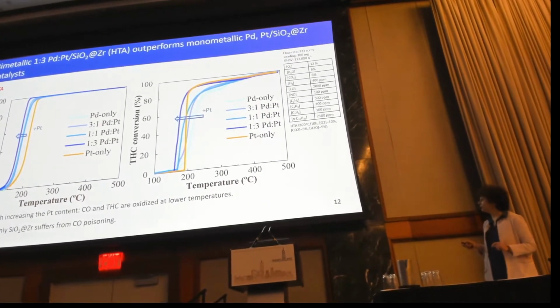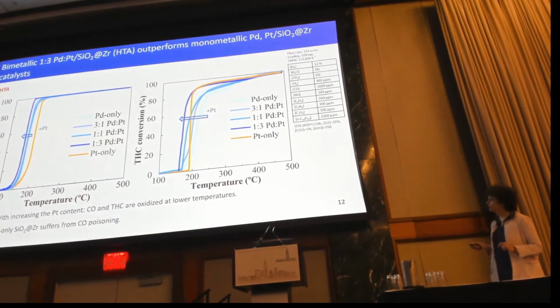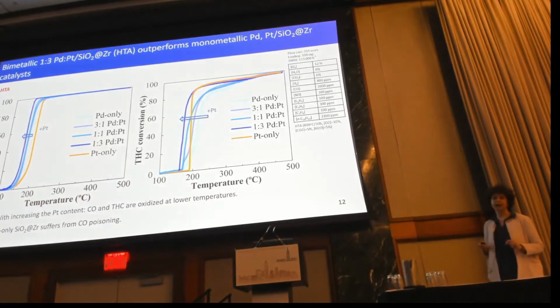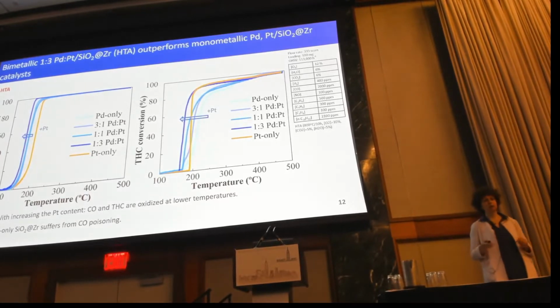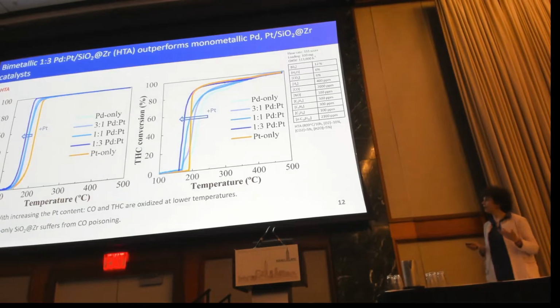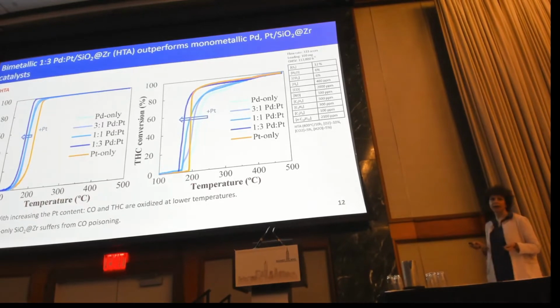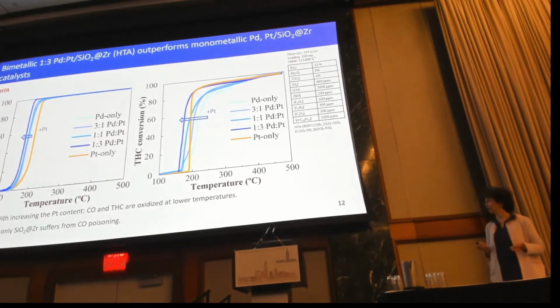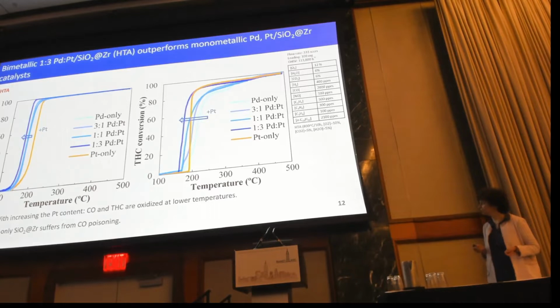So, one of the reasons we think that platinum is not such a good catalyst is because platinum has CO poisoning, so basically the majority of CO has to be oxidized first before we see hydrocarbon conversion, and that's why we see this sharp line of curves for the hydrocarbons in the case of platinum.